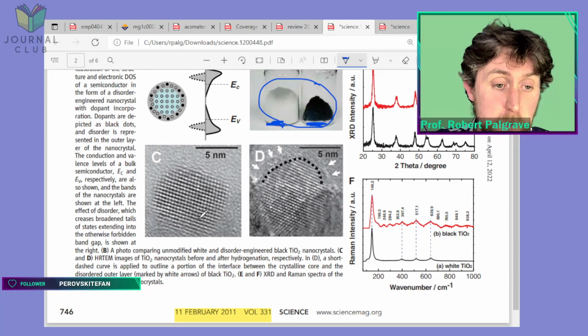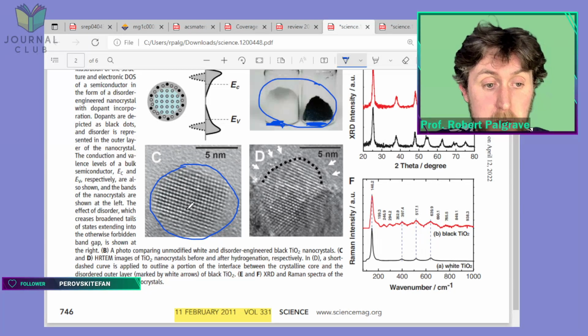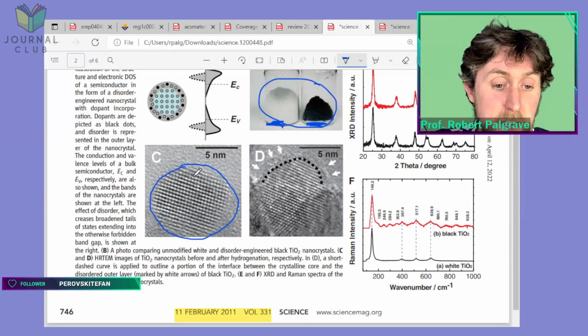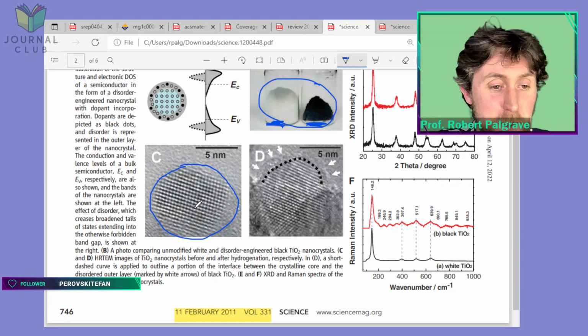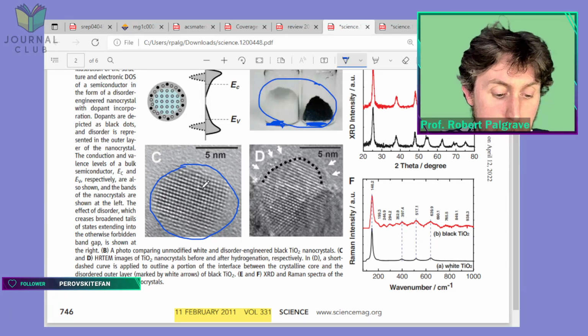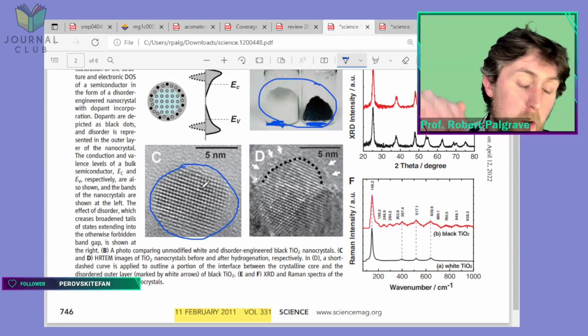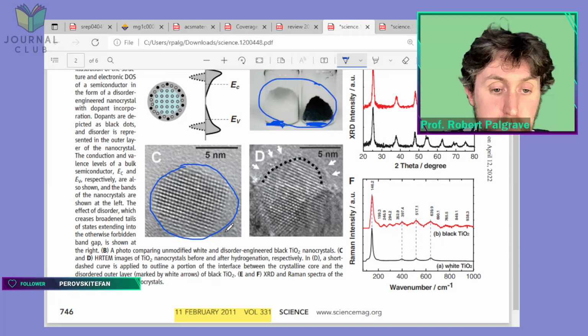They looked at some microscopy here, and so you can actually see with a transmission electron microscope the nanoparticle. So this is the nanoparticle here. The little dots inside, these are the atoms. These are the atoms in a nanoparticle. So TEM is an amazing technique, really. It really lets you zoom in pretty much as far as you can zoom in. You don't get much higher resolution than seeing the individual atoms. Of course, what we're really seeing here is a column of atoms going down rather than just one atom.